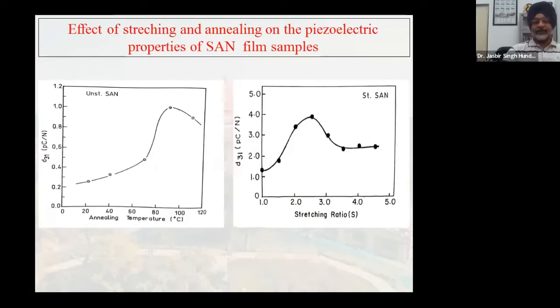Now, in the case of polystyrene acrylonitrile, there's one more thing. In addition to stretching, sometimes annealing is also done, because we prepare the films with the solvent cast method. So we try to anneal the films, and the best annealing temperature is 85. By annealing, any residual solvent in the film gets vaporized, number one, and then any stress created within the film while removing it from the glass substrate gets taken care of. So when you anneal a film, small stresses and strains that develop while it is being handled get removed. Extra solvent gets removed. So overall, crystallinity improves.